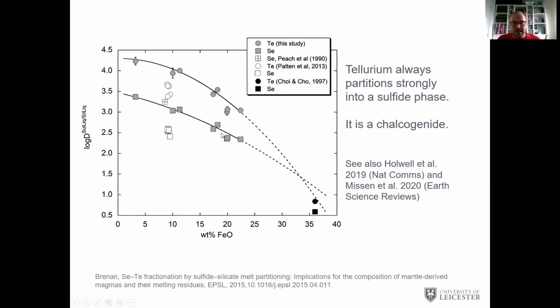Really what we're looking at is that the partitioning of tellurium into a sulfide liquid over a silicate liquid is really high. So this is in log. So orders of magnitude more tellurium will move with the sulfur than with a silicate melt. This situation changes somewhat when we start to form crystalline sulfides and we form minerals.